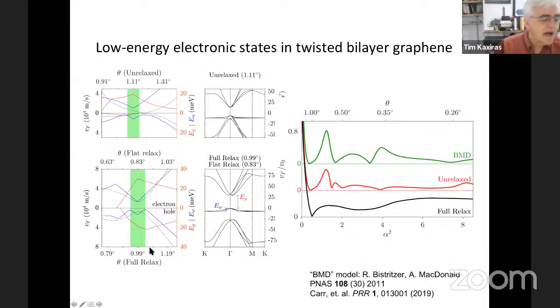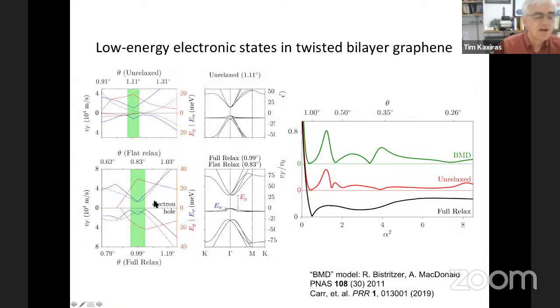And you see that as you change the angle and you make it in a small region around 1 degree, then all these features become optimal. The bandwidth, the blue, becomes the smallest possible value. The band gap, the separation from the other states, becomes the largest possible value, the red lines. And the Fermi velocity, the dashed black lines, becomes also smallest. The Fermi velocity is, of course, the flatness of the band. So you have very small Fermi velocity. But there's a region where these features are optimized. So it's not just a single angle, it's a range of angles. It's not just one magic angle value, it's a small range of magic angles.